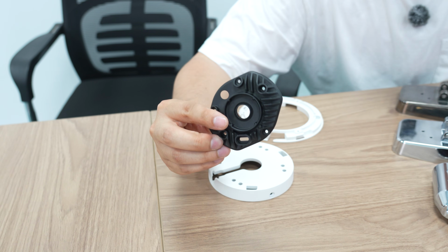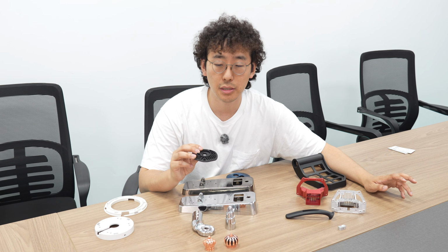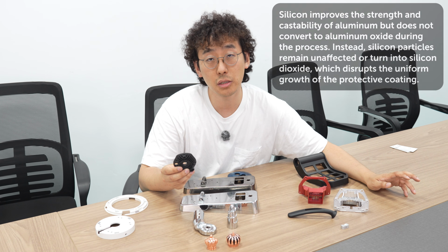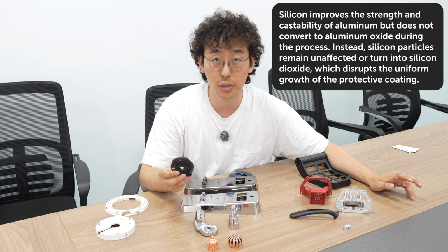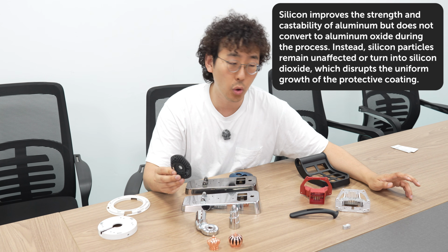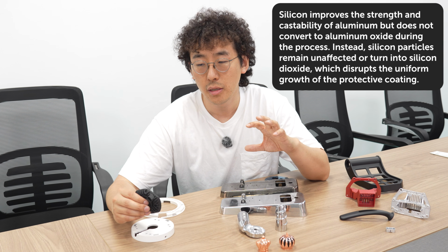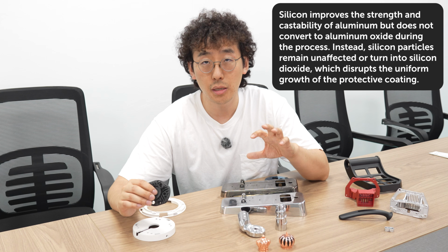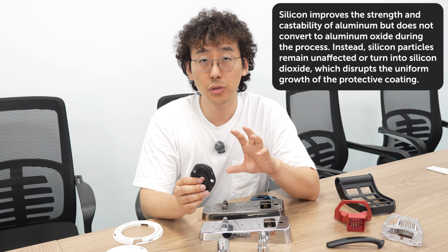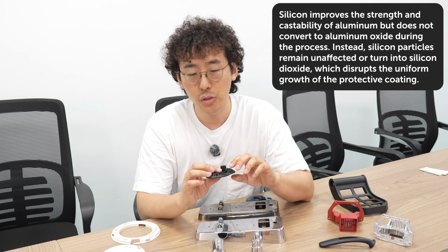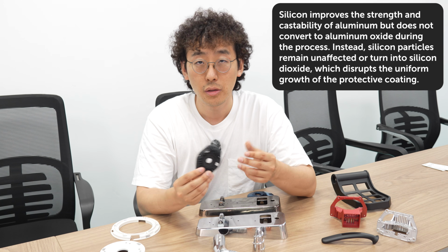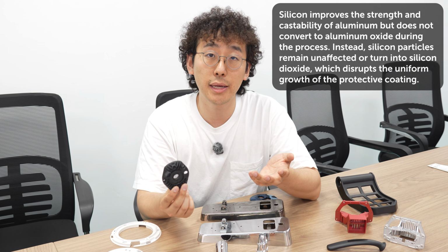One thing to note is that while these may look like anodized parts, actually this is the only anodized component. Why this is that with die-cast parts, silicon is added to increase the flowability of the aluminum alloy. The silicon content in die-cast aluminum makes it unsuitable for anodization. It's difficult to control anodization color. So if you want to anodize die-cast aluminum, the safest bet is to anodize it black.